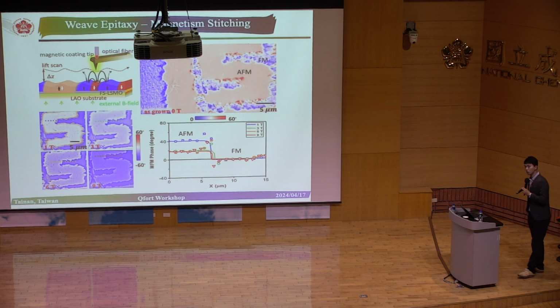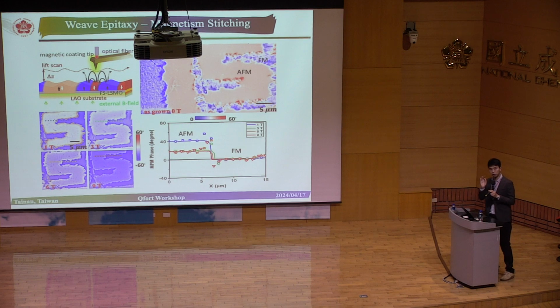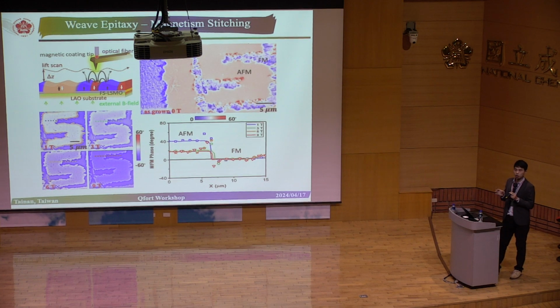If you have been to the second floor in the Department of Physics, in QFort, basically we have a very, very nice low temperature scanning probe microscope, where we can go to low temperature, but we can also apply a high magnetic field. So this is something that we have. If you look at the typical picture, we do it at 10K, all right? You simply enlarge the pattern L and S.